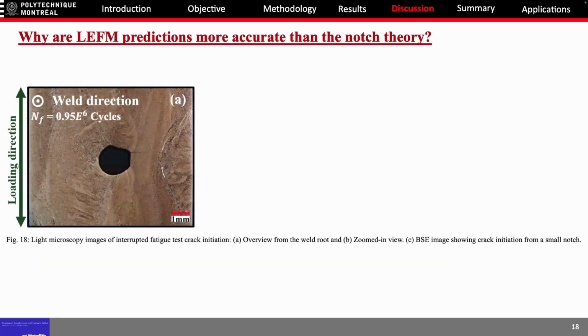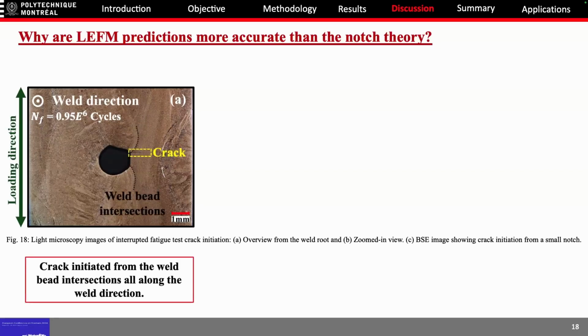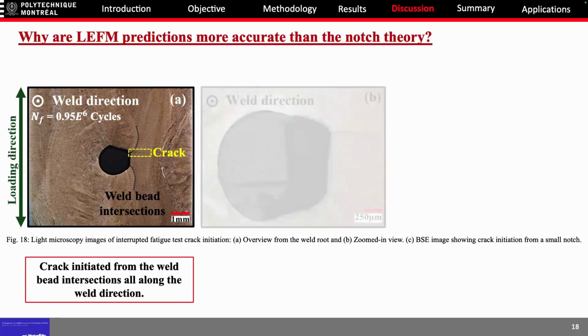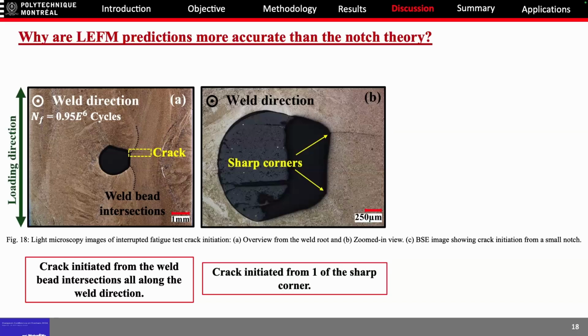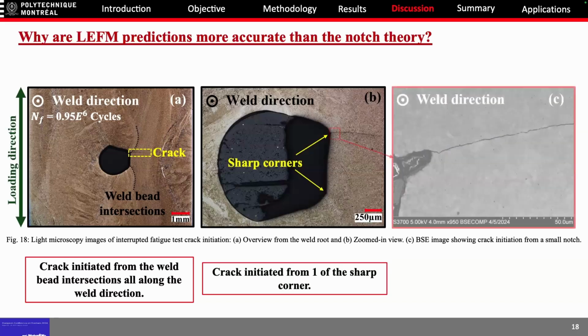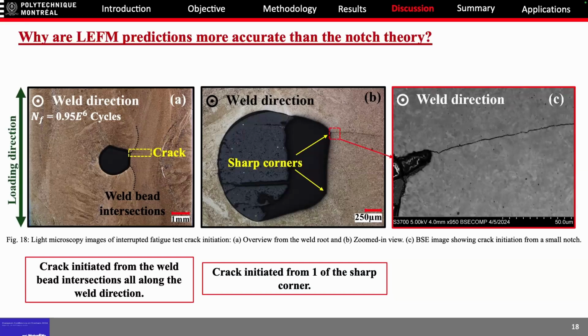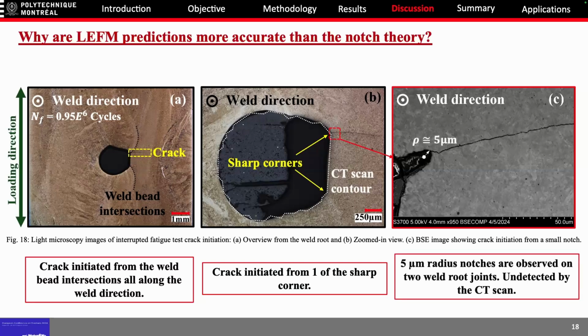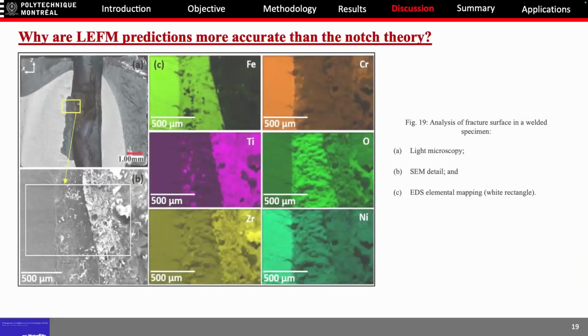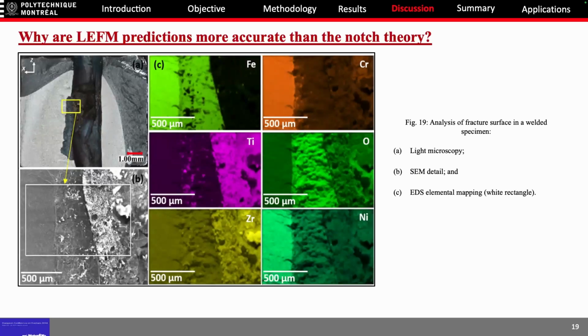So this is the interrupted test. You can see in black the discontinuity, and a crack emanates from the weld root between weld beads at intersections. A zoom-in picture shows us that there are two sharp corners, and one crack is emanating from a sharp corner. Another zoom-in picture shows us that this crack emanates from a small notch-like feature, and this small notch has an approximate radius of 5 microns. The CT scan contour shows us that it was undetected by the CT scan.